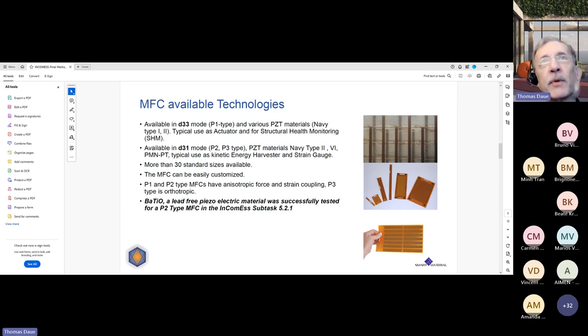The new device is the D31 MFC, what we call the P2 or P3 type. And they are available in different PZT materials, the Navy Type 2, Navy Type 6, 5A, 5H material. And in the past, growingly in single crystal. The InComEss project did not touch single crystal, but we have measurements that single crystal outperforms PZT on the one page by more than 60%. So from those 18 milliwatt we tested in work package 5.2, you basically can get all the way up to 28 or 29. The only disadvantage of single crystal is that it's almost prohibitively expensive.